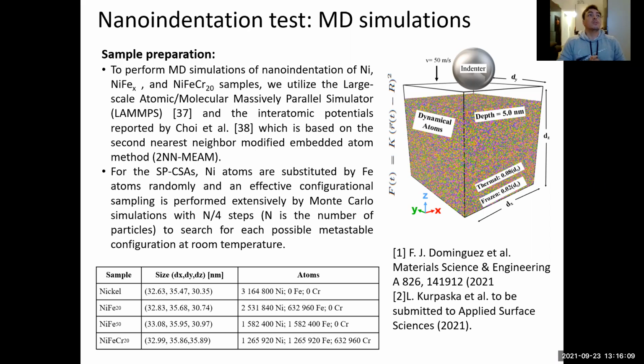So here we are using the reported interatomic potentials developed by Choi et al., which are based on the second nearest neighbor EAM. They are fit to experimental data, and they have been tested by your friend René, who is an expert in bulk metallic glasses, and he has been calculating all the thermodynamic properties of the high entropy alloys by using these potentials, and he's really sure that everything, the mixing entropy, everything, has good agreement with the experimental data reported in the literature.